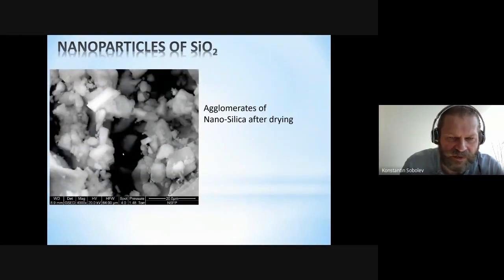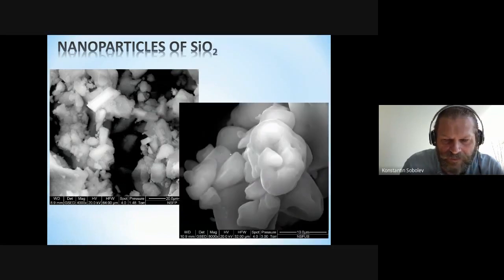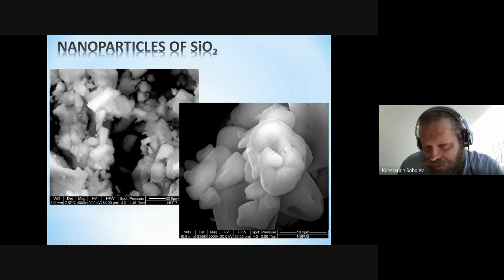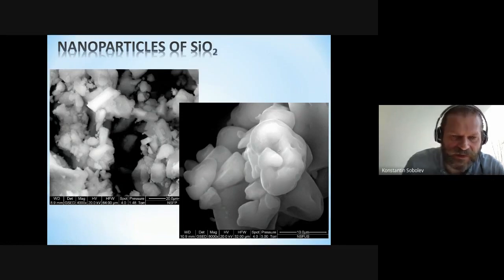And when we have nanosilica produced by the sol gel method, you can see the xerogel results in these sorts of chunks, which are relatively large particles. But if you zoom in, of course, you understand those are agglomerates of nanoparticles. If you just start using ultrasonification, you can see these angular particles becoming more round. Due to cavitation, the agglomerates are destroyed and smaller particles are released.